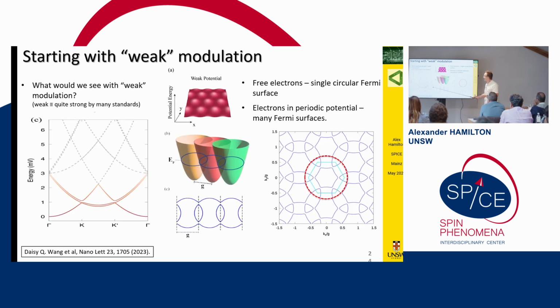If I now increase the modulation, what happens is my parabolic band gets some small structure on it. I don't open up band gaps yet, but I get a small anti-crossing here. And so I get copies of this first Fermi surface happening again here at k plus G, and then again at k plus 2G, and again at k plus 3G. And that's how we teach the origins of band structure to undergraduates.